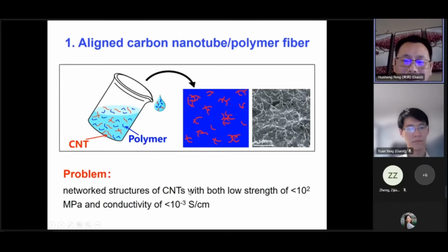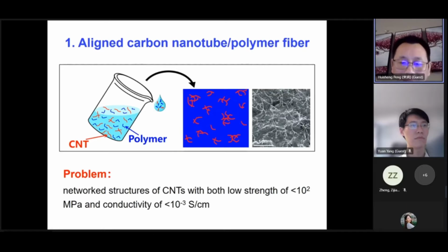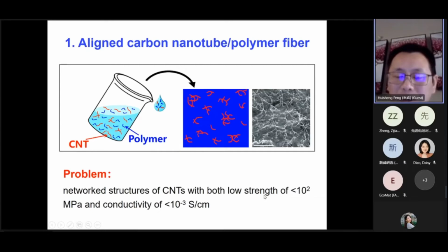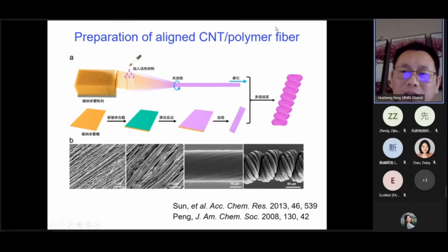Indeed, many people have done work in this direction. Many people just disperse carbon nanotubes and polymer in a solvent, and then by evaporating the solvent in a solution process, they produce bulk materials or composite films. The main problem is that the carbon nanotubes aggregate to form network structures. We try to take advantage of the high mechanical and electronic properties of carbon nanotubes, but in fact the composite materials show very low strength and very low conductivity. That's a big problem. The poor properties come from this networked structure, this aggregation. So we try to align the carbon nanotubes in the composite materials, focusing on fiber materials.